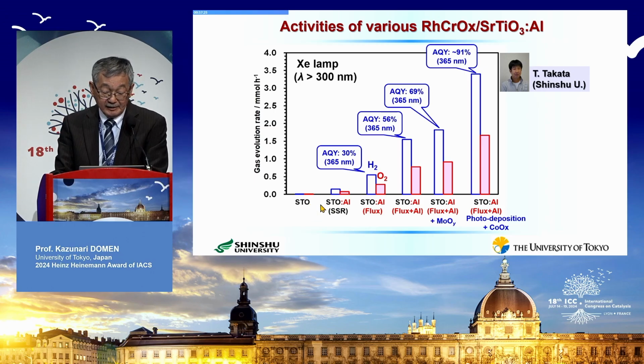After that, we modified the properties of the strontium titanate. Here, I focus on the aluminum-doped systems. And when we used the so-called flux method, at this stage, as you see here, the apparent quantum yield already exceeded 50% at 365 nanometers.